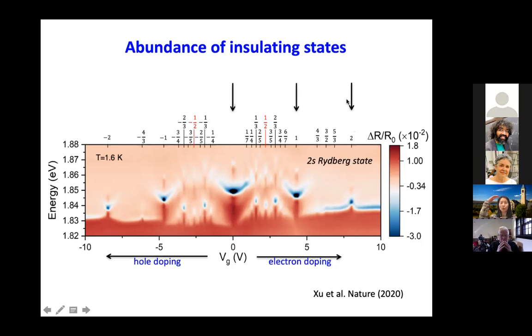Now, if I come in with 2 electrons per Moiré site in my sample, I still see this insulating state. The same thing happens if I load holes into the sample. So basically, we have a way to see whether the sample is insulating or conducting. Every time you see those blue, large-intensity absorption features, that means my sample is insulating. We also saw some fractional filling states, and that tells me my sample is insulating at those fractional states. In between, we have a conducting material. So how do we understand something like this?